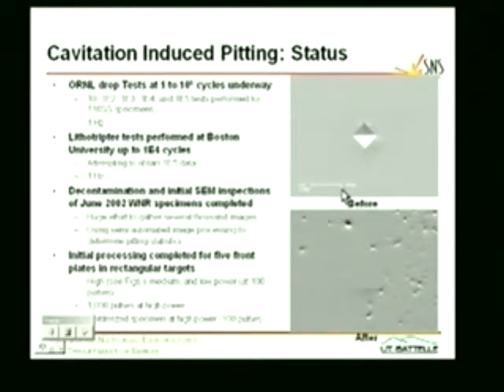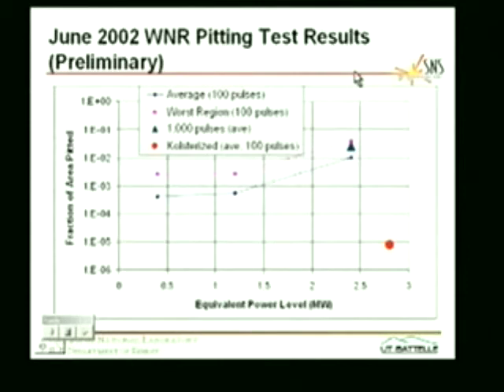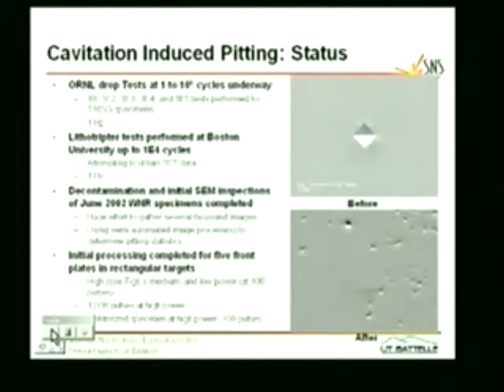One of the issues we've been grappling with is the lifetime of the stainless steel vessel that houses the mercury that is the target. And the issue there is something called cavitation-induced pitting. This shows an electron micrograph of a coupon of 316 stainless steel before and after a beam irradiation experiment at the WNR facility at Los Alamos, and you see before it's quite pristine, and afterwards you have these little dimples.